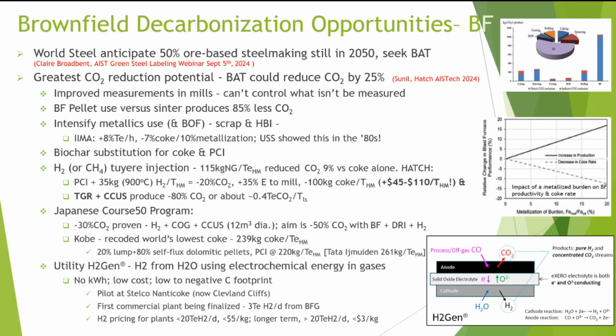It's shown that 115 kilograms of natural gas has basically reduced CO2 9% versus coke alone. And Hatch has predicted that if you use PCI, 35 kilograms of 900-degree hydrogen, you can get 20% reduction in CO2 and an additional 35% of energy to the steel mill, but it's going to cost a lot, even though there's 100 kilograms of coke reduction. If you add to that top gas recycling and CCUS, you can potentially produce an 80% reduction in CO2, which would bring the emissions from a blast furnace down to 0.4 tons of CO2 per ton of liquid steel, which is almost as good as 100% scrap in an EAF without renewable energy.